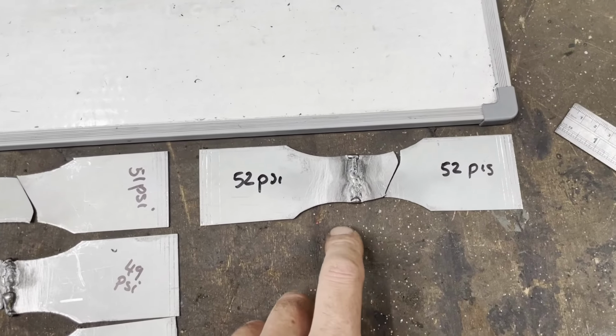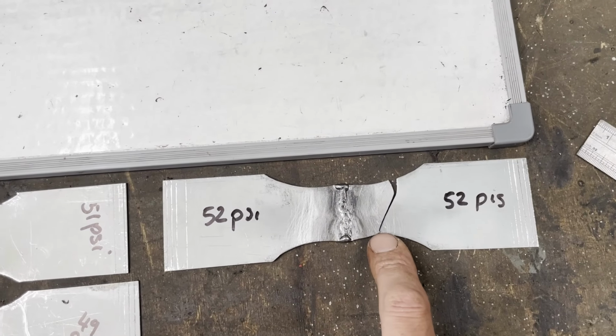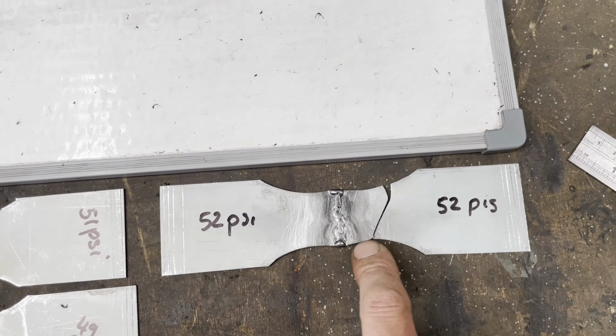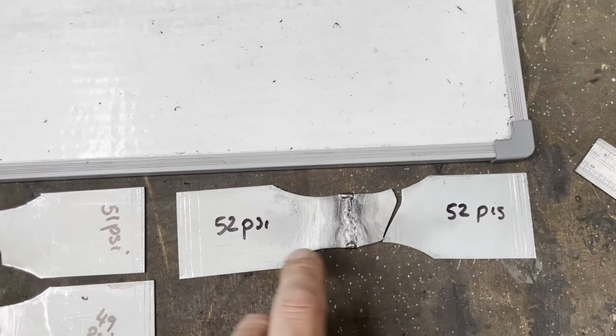TIG with filler rod then did very well. Didn't actually break at the weld at all. It broke up here, so it must have been a slight defect up here, but nothing wrong with that whatsoever.